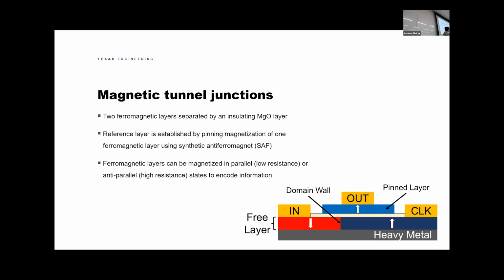And in this example specifically, we have an SOT, spin orbit torque, magnetic tunnel junction. And I'll get into that next slide, why that's important. But otherwise, when we're in our parallel state or a low resistance state, we have both of our ferromagnetic layers magnetized in the same direction. And that means that in this example, they will conduct spin-up electrons very easily. But when we enter our anti-parallel high resistance state, so we have our pin layer spin up and our free layer spin down, it will scatter electrons of both polarizations and lead to a high resistance.